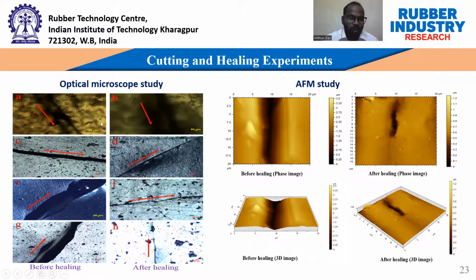So this is the control sample, meaning without metal ion. In the optical microscope study we have seen that it is not healed at 80 degrees centigrade after 24 hours. This is the nickel modified compound, which is also not completely healed. And for the cobalt modified compound, this is before healing and this is after healing, which is healed but not fully healed. And the zinc modified compound, at 80 degrees centigrade after 24 hours in the optical microscope study, is completely healed.